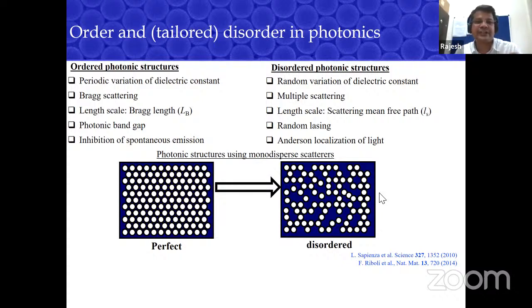Okay. So in ordered photonic structures or photonic band gap structures, you have periodic variation of dielectric constant, we have Bragg scattering, we have photonic band gap, we have inhibition of spontaneous emission. This is what we studied till now. Now, when you talk about disordered photonic structures, instead of periodic variation of dielectric constant, you have a random variation of dielectric constant. And instead of Bragg scattering, you may have multiple scattering because you don't have any preferential ordering. So the light can take a very crazy path within the system. Instead of Bragg length, you have a scattering mean free path, the distance between two scattering events. And there are phenomena like random lasing or Anderson localization of light, like Anderson localization for electrons. That's why these systems are quite interesting.